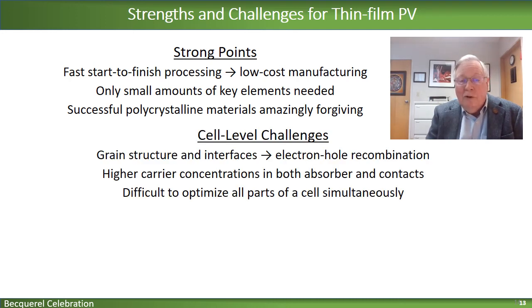Cell level challenges going forward are that there are unsolved problems with grain structure, and in particular at the interfaces where the electrons and holes tend to recombine and in that case don't contribute to external current. We're looking to increase the carrier concentration in both absorbers and contacts. And probably the biggest challenge is to get everything to work right at the same time.